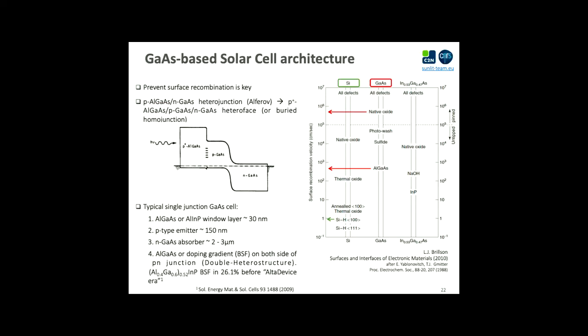Of course, the structures evolved afterwards, for example, by replacing this AlGaAs with an even higher bandgap material, for example, aluminum indium phosphide, reducing the thickness of this material down to a few tens of nanometers, adjusting a little bit the thickness of the emitter and the absorber. Now, I think Alta Devices is in between 1 and 2 micrometer thick base. And they also introduce a so-called back surface field or a double heterojunction here also on the right side to prevent recombination on the back side of the cell.